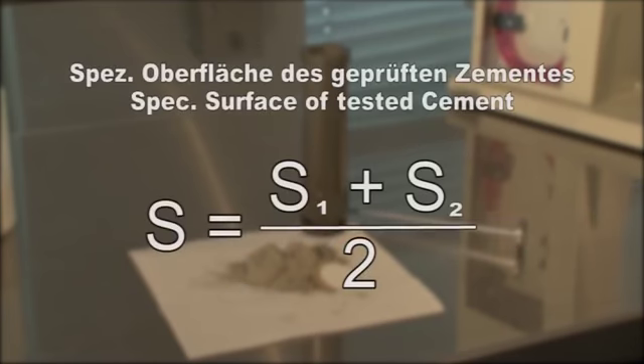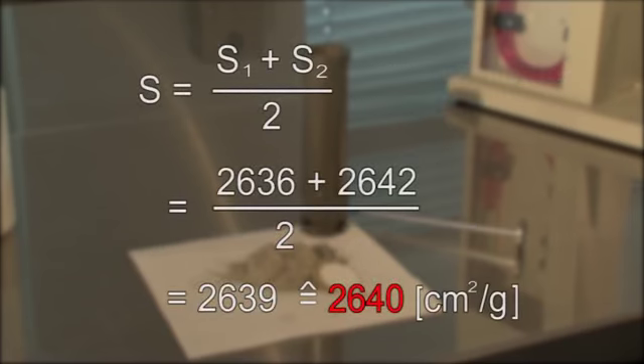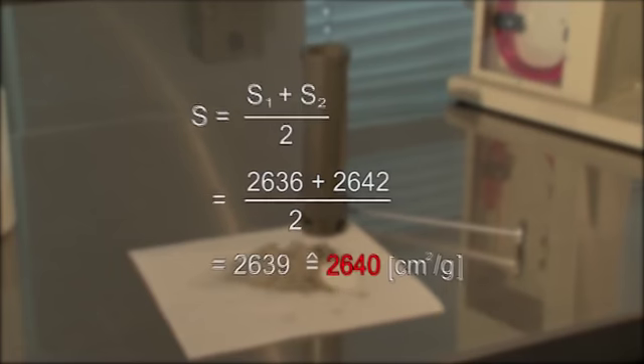Two samples must always be tested in order to establish the total mean value S of the specific surface area. A mean value is now calculated from the specific surface area S of the samples 1 and 2. The value is rounded to the next 10 square centimetres per gram.